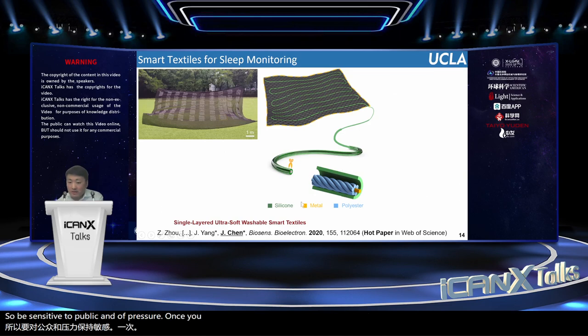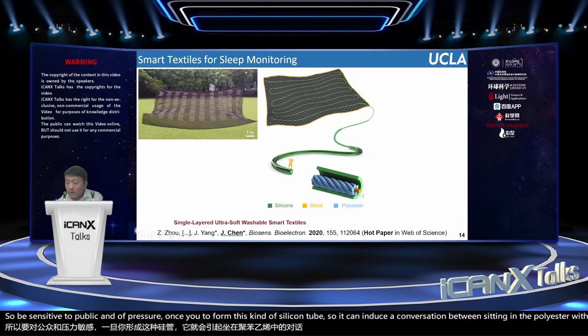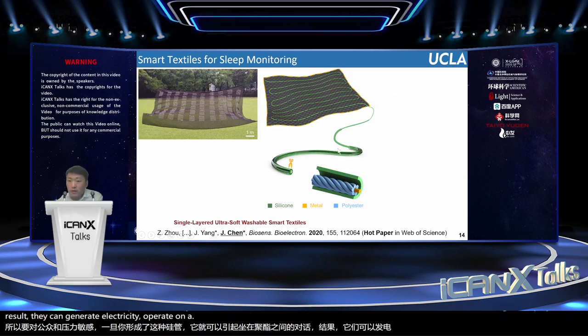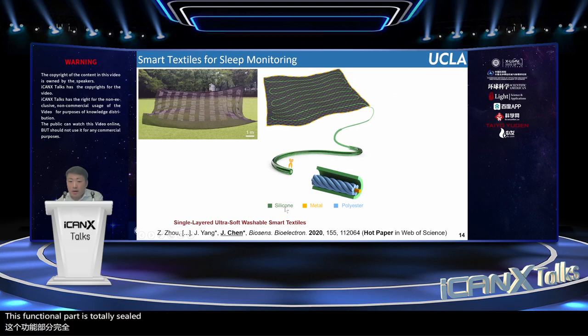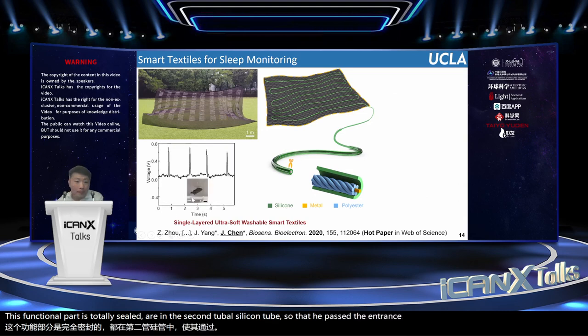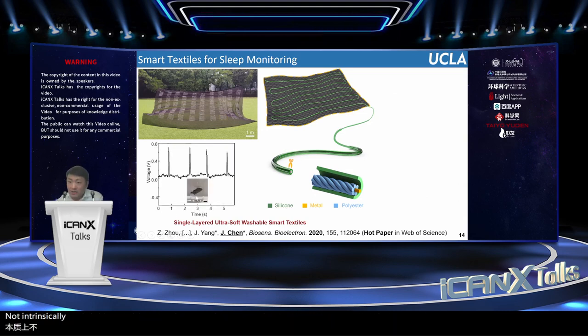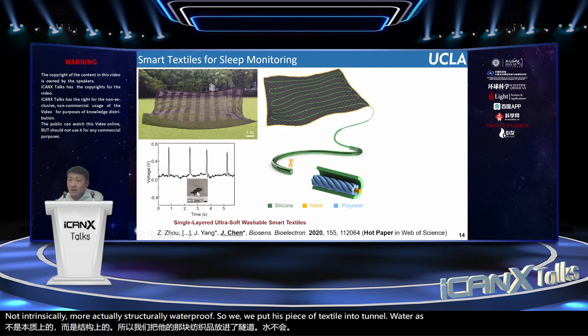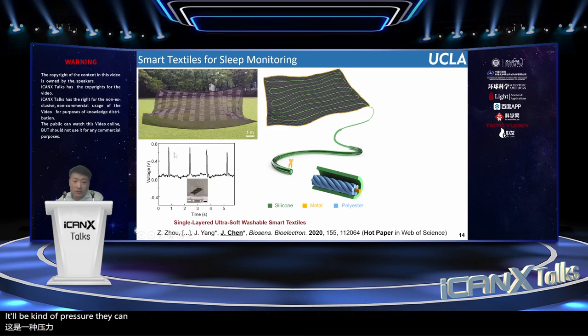Once you deform this silicone tube, it can induce a contact separation between silicone and polyester. As a result, it can generate electricity in a circuit. Because this functional part is totally sealed in the silicone tube, the device is structurally waterproof. So we put this piece of textile into a tank of water. As long as you add mechanical pressure, it can generate voltage up to about 0.8 volt.